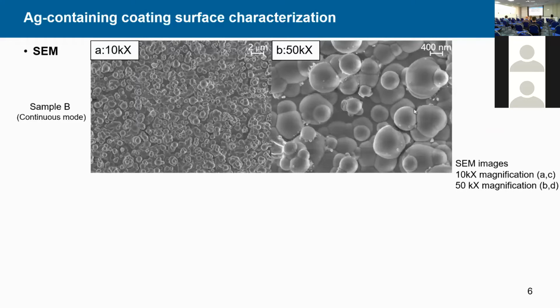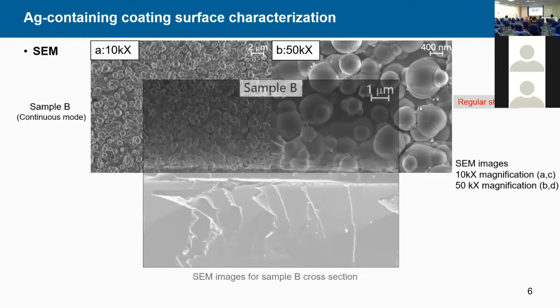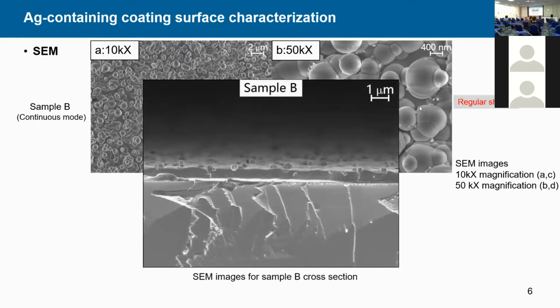Now let's look at the SEM images of sample B treated under continuous mode. The left side gives the image at 10,000 magnification, and the right side shows the image at 50,000 magnification. We find that there are many nanocapsules or nanospheres with regular shape in the coating. We also checked the cross-section of sample B and found that the coating consists of a layer of polymeric matrix with nanocapsules embedded inside and grafted on the coating.